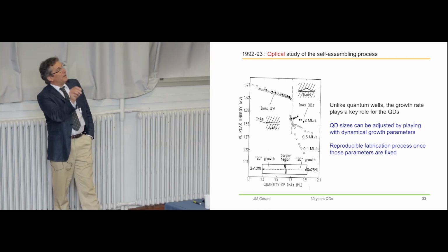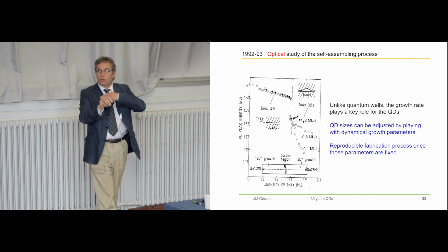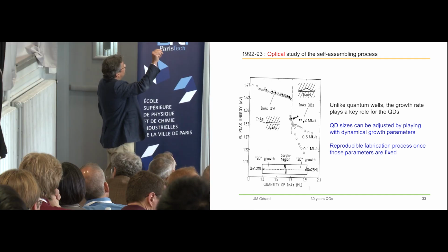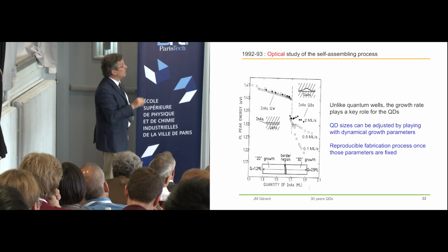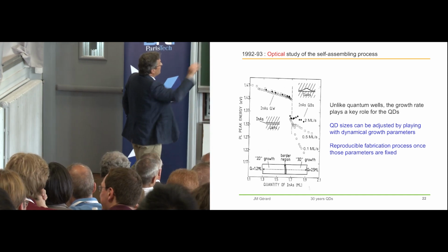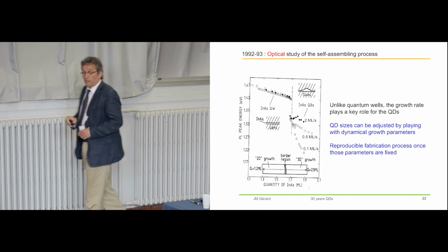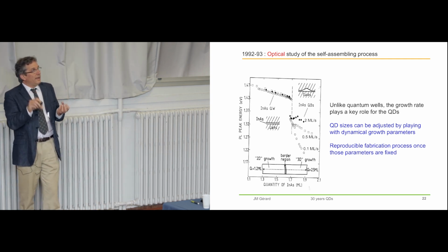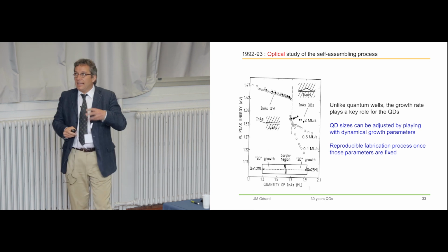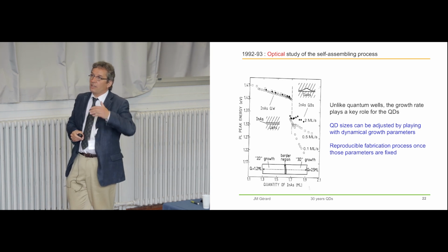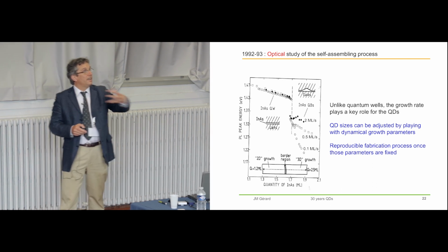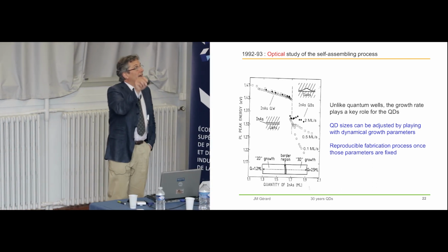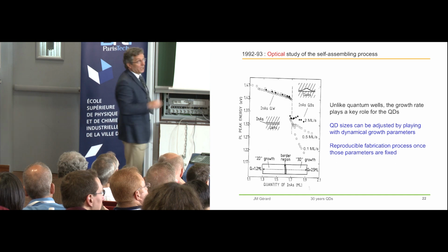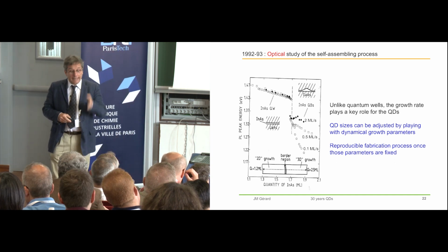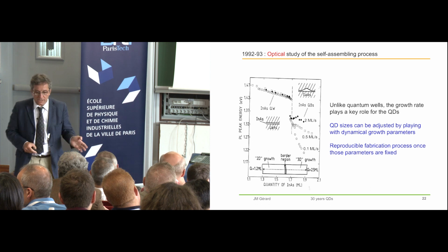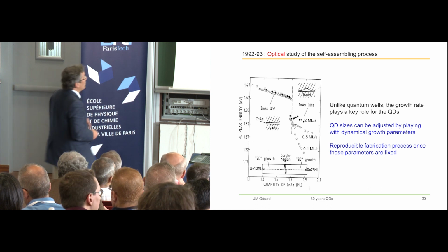You can see also in these experiments that when you play with the growth rate, the properties of the quantum well do not change. However, the properties of the quantum dots change a lot. The properties of your quantum dot array can be adjusted by playing with dynamical growth parameters, such as the growth rate or such as growth interruptions. As soon as we had understood this point, we fixed the growth rate and so on, and the results of the fabrication process became perfectly reproducible.